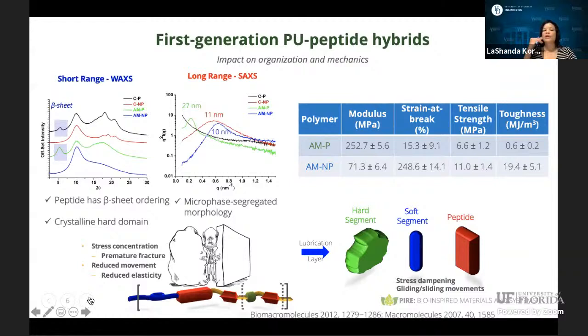The next question that we wanted to see is really, are we achieving this hierarchy? So we saw images of weak phase segregation, which from a long range order standpoint, looking at the small angle X-ray scattering, is consistent and very typical of polyurethane ordering. From a short range ordering, though, we saw two things. One is that for those systems that had peptide included, you actually were able to retain the beta sheet structure, but you also were able to see the hard domain organization in these systems.